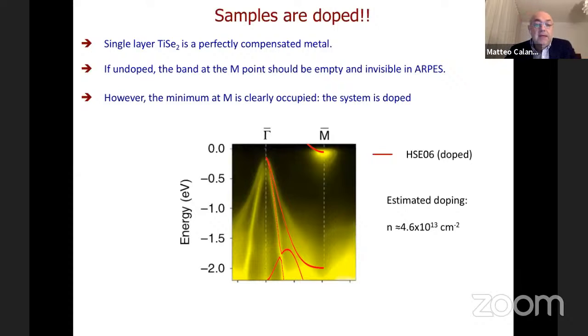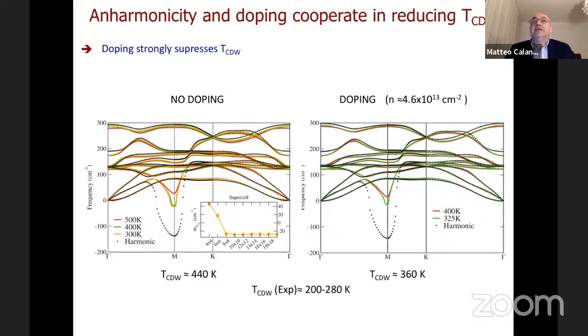So what happens if you consider the cumulative action of doping and anharmonicity? You can see here that at the harmonic level, the two spectra with no doping or with doping are practically identical. So you don't see any difference. However, if you look at the anharmonic spectra, the results are substantially different. And in particular, there is a combined effect of anharmonicity and doping. This is because the anharmonic correction depends on the change of the phonons at all points in the Brillouin zone and on all the phonon band indices. So it means that any change, also at high energy and everywhere, affects the phonon. So small changes are enough to make a different anharmonic correction in the case with doping or without doping.